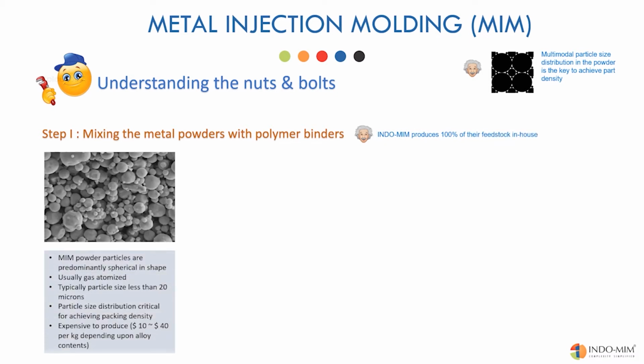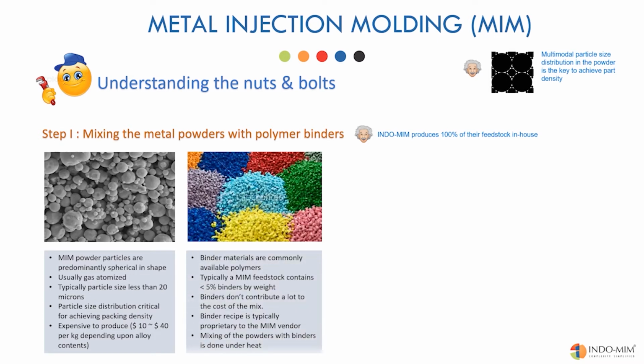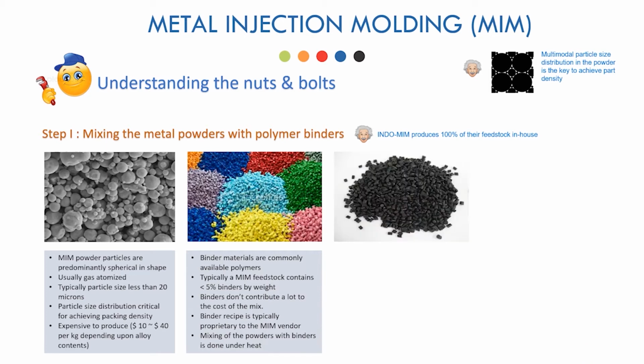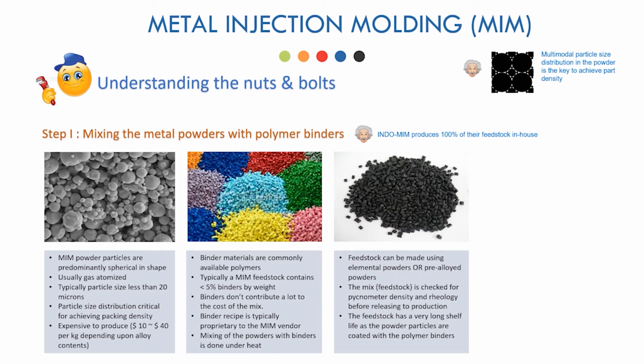Metal powders are normally produced through gas atomizing. The gas atomization process produces spherical-shaped particles. Round-shaped particles flow better during the molding process. Typically, MIM powder particles are less than 20 microns, significantly smaller than metal powders used for the conventional press and sinter process. The powder contains particles between 3 microns and 20 microns in precisely maintained particle size distributions. This is extremely critical to achieve the best possible powder packing in a molded component.